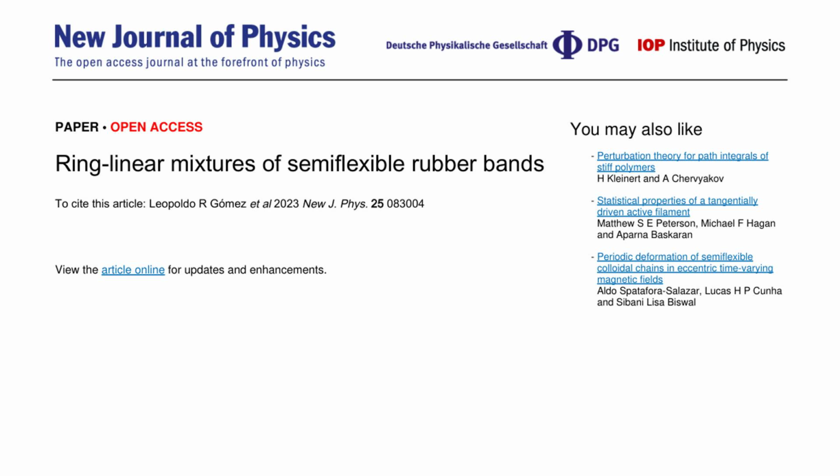The introduction also provides a brief overview of the challenges in studying ring polymers compared to linear polymers. Rings do not have ends, which means they cannot reptate like linear chains to renew and relax configurations after external stress. The behavior of rings in terms of structure and dynamics remains elusive, and there is ongoing debate about whether tube theories can be applied to understand their relaxation dynamics.